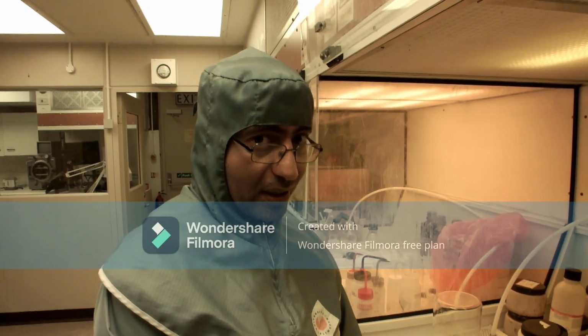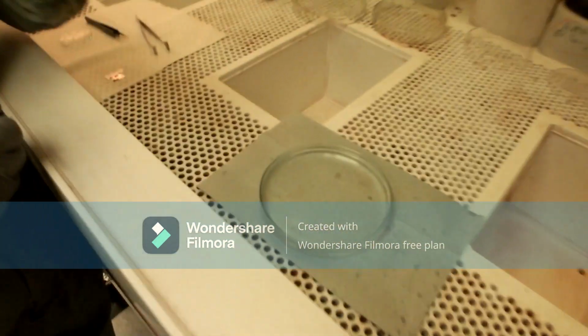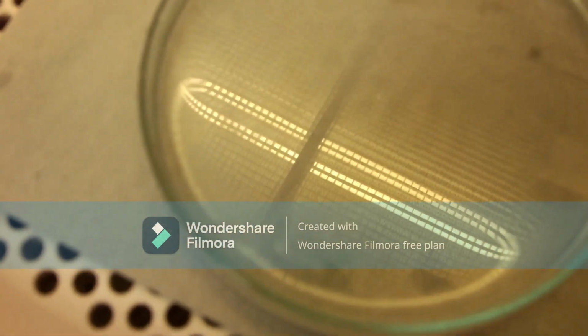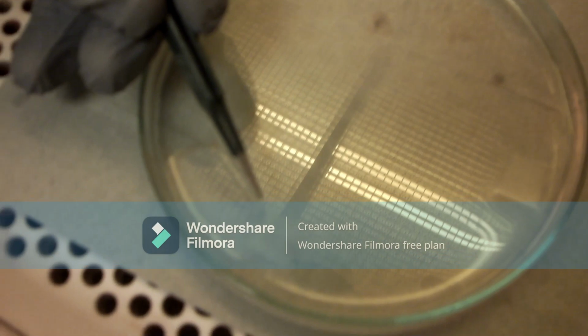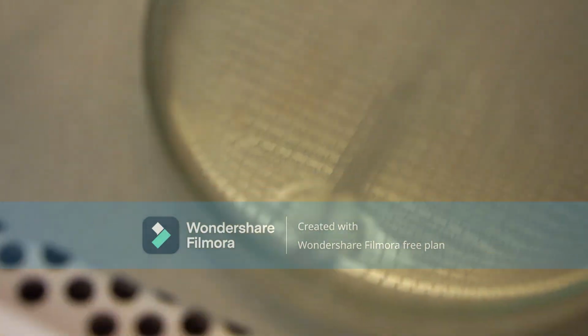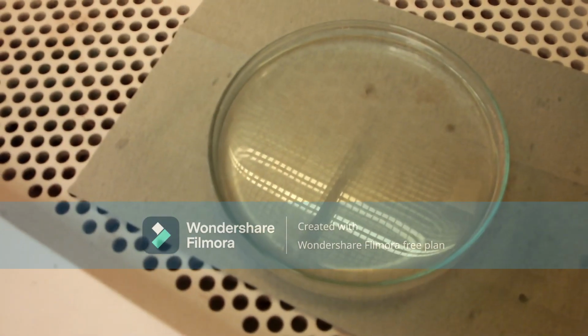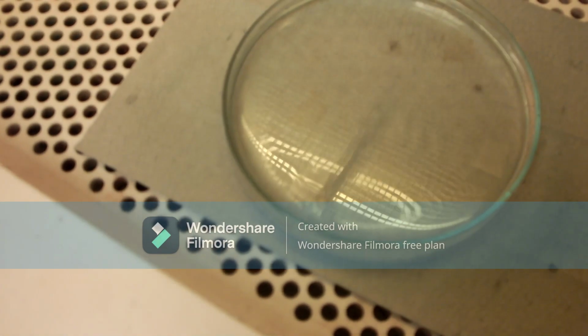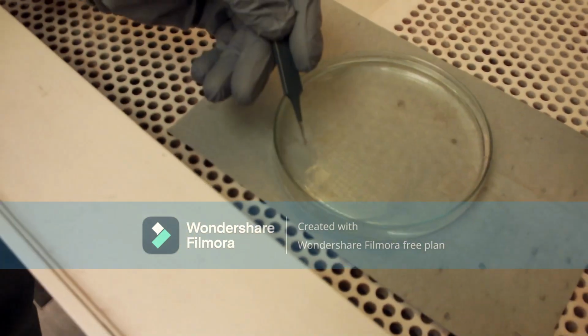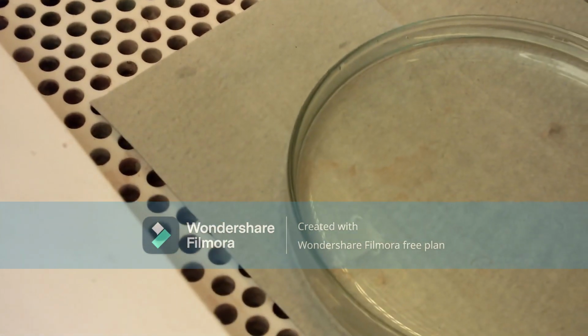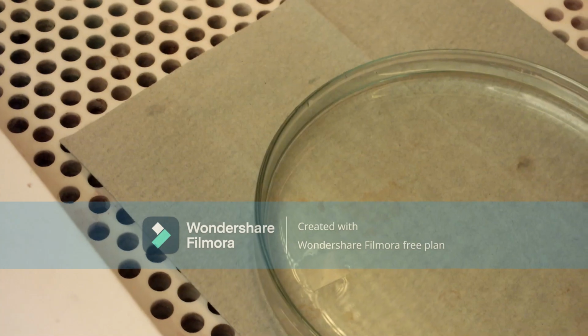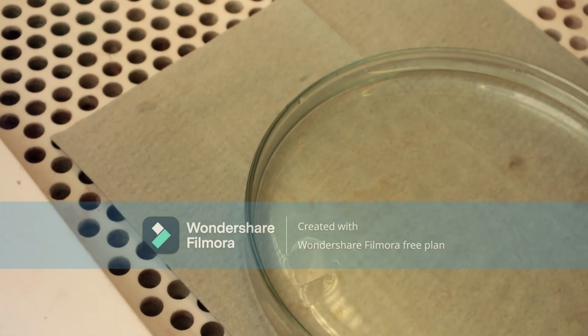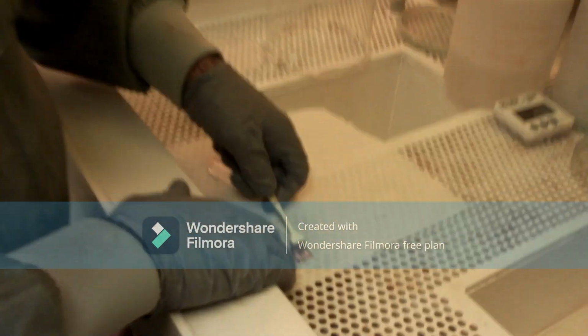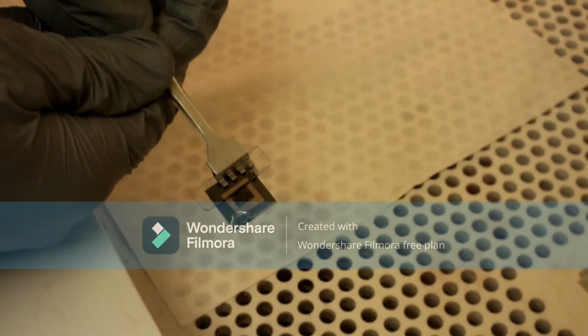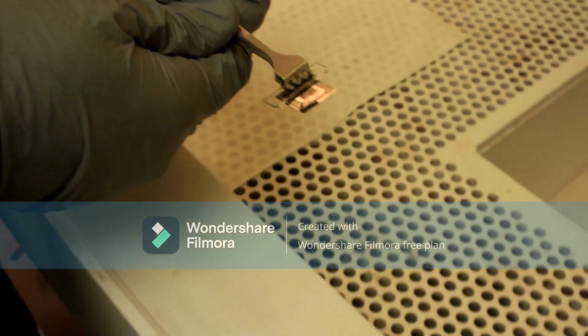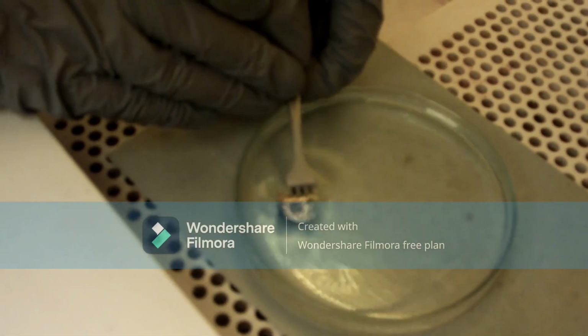After around 11 hours and a half, I can see a transparent layer floating in water. As you can see, I moved it from the ammonium persulfate to DI water, and I have to keep it for 20 minutes just to stop the etching process, to avoid affecting the graphene layer. Here, as we can see, there is the PMMA layer, and underneath there is a graphene layer. That's the first layer which I protected with the PMMA. Now I need to transfer the graphene to the empty square here in the middle. This is to complete my device, and you will see the transferring process.